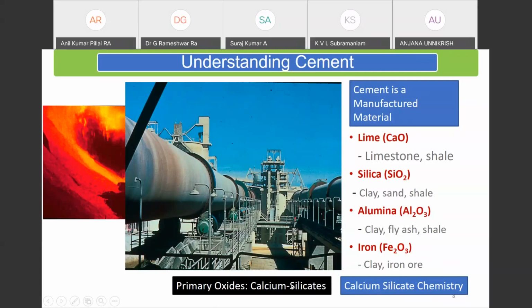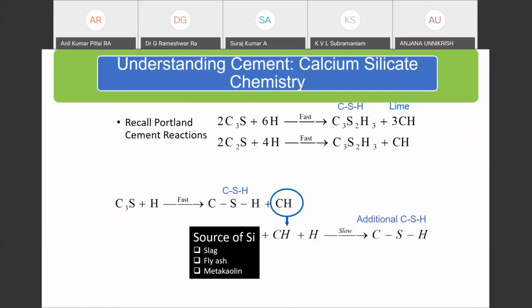And everything that has come about from cement, when we mix it with water, and as it hardens, as it gains strength, is basically driven by calcium silicate chemistry. And that is what we have been using for the past 2 centuries in the form of Portland cement. A little bit of chemistry: basically calcium silicate. So what you see here are tricalcium and dicalcium silicates. Those are the main ingredients of cement. When they react with water, which is shown with the H here, it produces CSH, the calcium silicate hydrate. This is the material that gives strength to concrete.